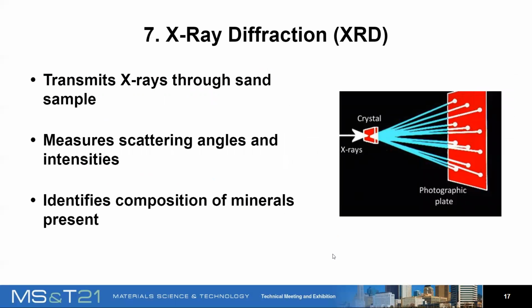Then moving on, this is our X-ray diffraction. Essentially how this works is that you shine the X-ray through your sample. In this diagram, it's a crystal, but we're going to put our sample in here as the sand particulates. And after the X-ray goes through, we're going to get some X-ray scattering. And after the rays scatter, we're going to measure the scattering angles. This is important because once you get the scattering angles and intensities, you're able to tell the mineral composition of what your sample contains.